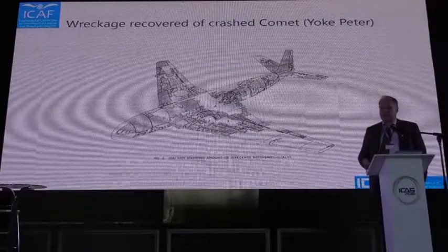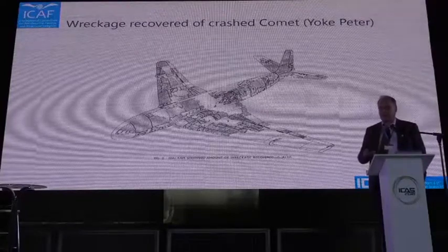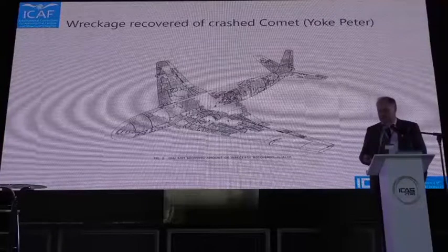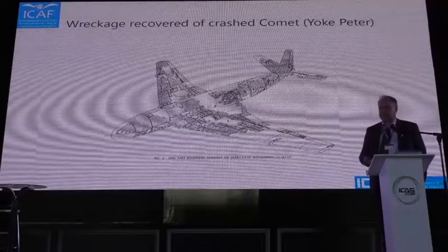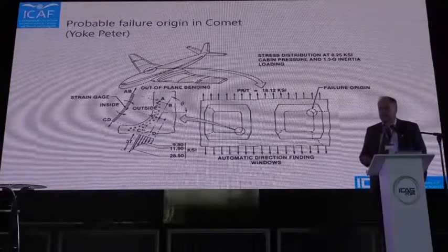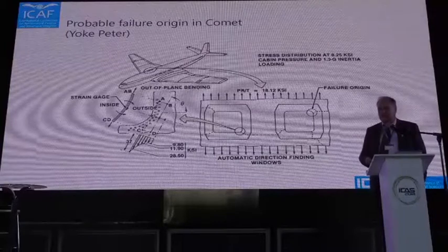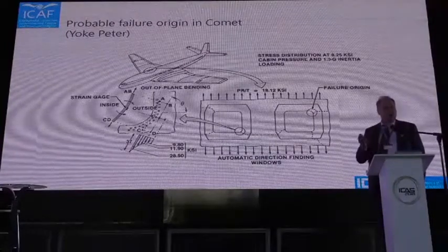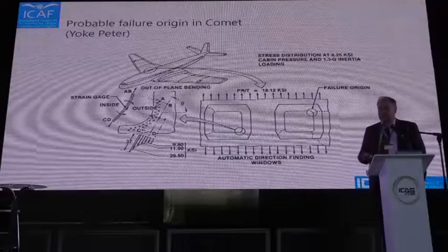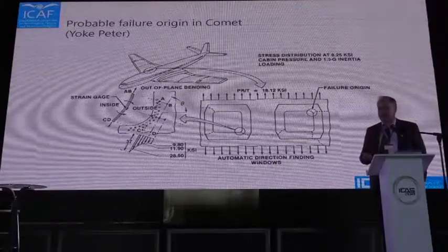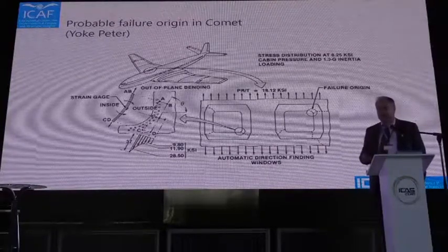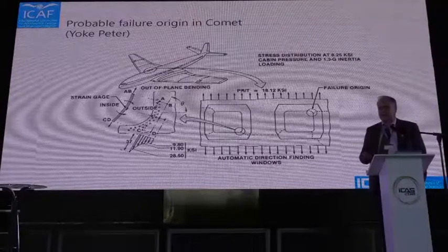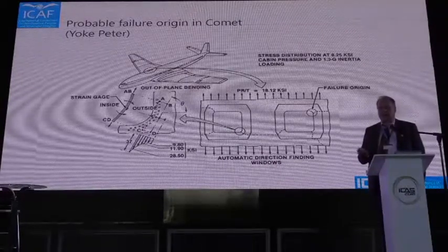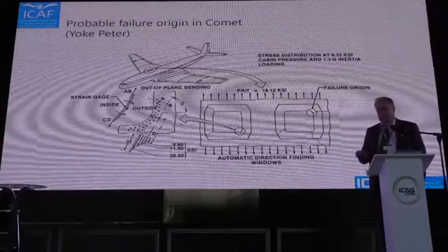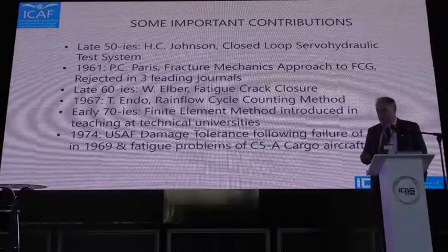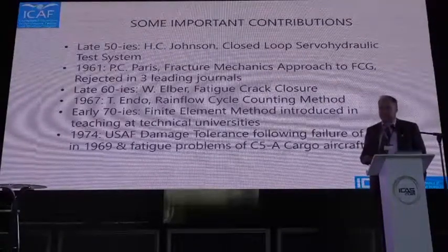Then they tried to recover the pieces from the first failure and started to do fatigue tests. And it was soon realized that fatigue cracks did happen, and they came at the corner of this window, which was used at this time to navigate after the stars at night. So basically it was understood already at this time that cracks initiated due to the very high pressure and stress concentrations. Later on, it has also been explained that we had lots of secondary out-of-plane bending due to curvature of the fuselage, which added to that. So the main effect here was basically to realize the importance of stress concentrations.